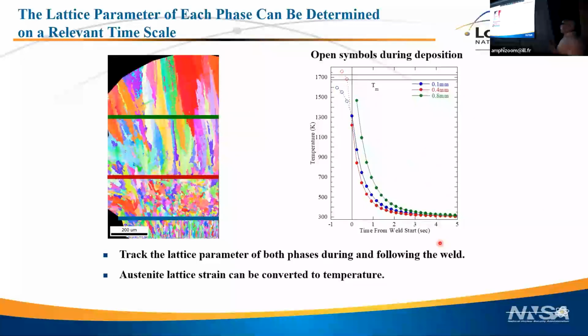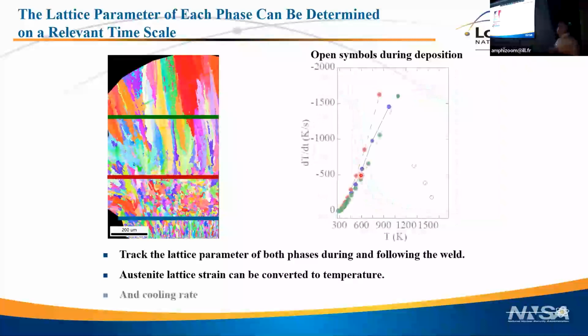So we can pull out the temperature as a function of time. So you can see it drops. These lines here kind of bound the melting temperature of 308 stainless steel, depending on the exact chemistry. So it actually forms right about where we'd expect it. This is, again, the solidification temperature. Cools very quickly. We can pull out the cooling rate. At the maximum, it's at about 1,000 degrees C per second, which is what you expect.